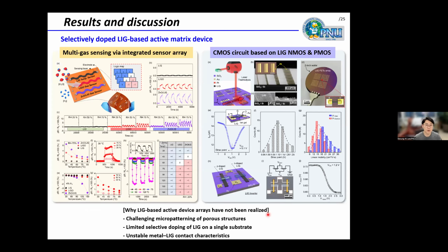By employing this solution-based laser ablation technique, we can realize active matrix devices that were previously difficult to achieve with the conventional LIG system. Until now, there have been several key limitations to realize active matrix devices based on LIG. The first is the challenge of precisely patterning the porous carbon structure, and the second is that there has been no reliable method for selective doping. Finally, forming a stable electrical contact with the three-dimensional carbon structure has also been difficult.